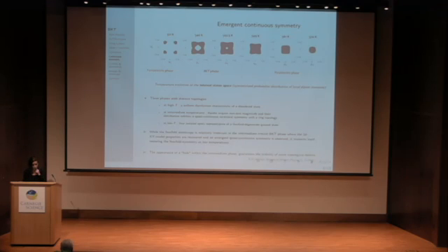So we do have indeed, it seems like it at least, that in this intermediate temperature range, so within the BKT range, we have an emergent continuous symmetry where the anisotropy only slightly distorts, as you can see, the shape of the ring, but basically guarantees, given the theory of Mermin for topological defects based on homotopy theory, that any topological defect, point-like vortices or anti-vortices, would be stable in this intermediate phase.